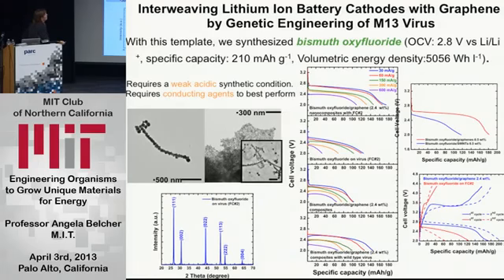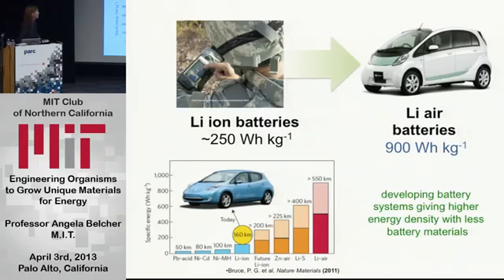And that through the additional genetic engineering, we could actually give it a higher capacity through controlling the genes that were coding for the ability to simultaneously bind the graphene, in this case grow the bismuth oxyfluoride material. So again, taking it to a different kind of material. And one of the areas we're looking at now are lithium-air batteries or lithium-oxygen batteries.